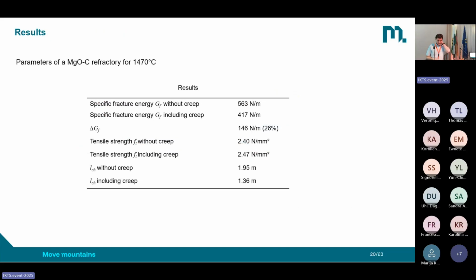And how much is it? You see on this table, without creep, we are getting 563 newtons per meter, and with creep, 417 newtons per meter. Again, a significant difference. What is important to know, for all of you doing this test, especially at high temperatures, is that the contribution of creep depends on the speed of the test. Because creep is time dependent, if you have more time, then you have more creep. So be very careful, because if you do a very slow test, then you will get a very low specific fracture energy, but a huge contribution from creep.